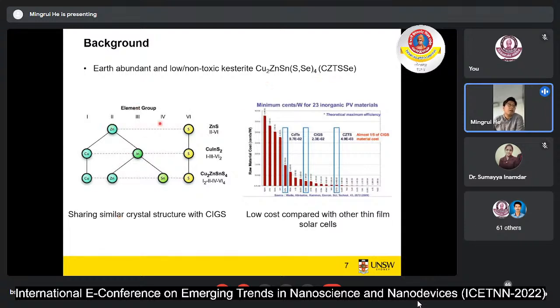To move on to the kesterite crystal structure, kesterite is actually derived from the zinc sulfide structure. The zinc in zinc sulfide can be divided into copper and indium. So copper indium sulfide is kind of the second generation of the zinc sulfide materials. After that, if we divide the indium into zinc and tin, we come to copper zinc tin sulfide. So basically, the CZTS crystal structure is similar to the copper indium sulfide structure.